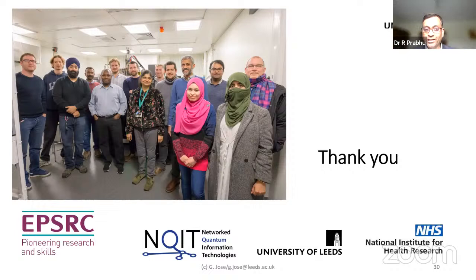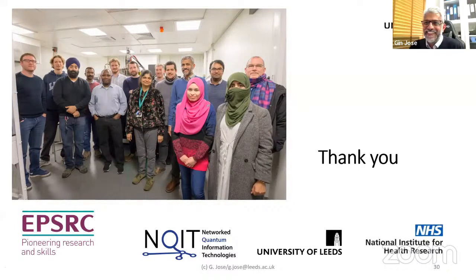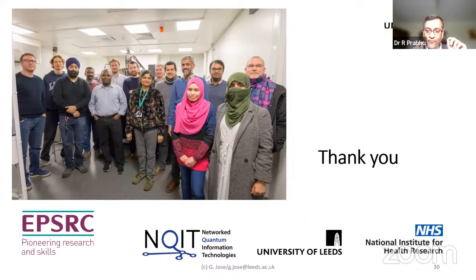Okay. And another quick one is on the TiO2. You last slide around, you put the TiO2 on it. So we previously worked on converting laser-based anatase to rutile for TiO2. While you are depositing, during deposition, is it possible to convert or change the composition of some of the anatase to rutile? Because there is a lot of application around getting a particular percentage of anatase rutile. So is it possible to?